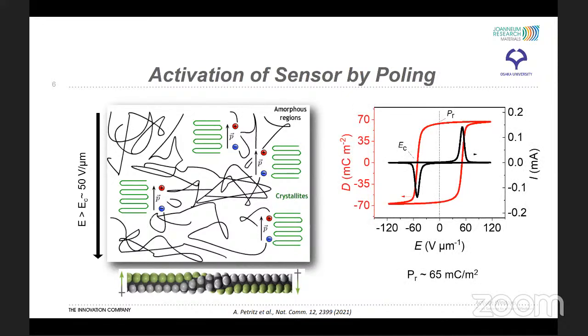The chain rotation produces a Poling current that peaks at the opposing coercive fields, shown in this graph in black. By integration of the area normalized Poling current, we can get the displacement hysteresis loop, which is something like a fingerprint of the ferroelectric material. It shows the typically bistable nature of the ferroelectric polarization. And from this hysteresis curve, we can deduce the most important key performance indicator of the sensor, which is the remanent polarization, which is also the displacement at zero electric field. For the ultra-flexible sensor, the remanent polarization which we got was around 65 millicoulomb per square meter, which is a very good value.